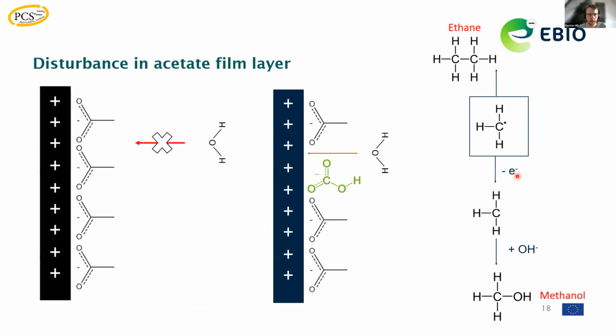So to summarize all this, what we think is happening is that we disturb our acetate film layer by the presence of the carbonate species in the electrolyte, thereby also allowing interaction of water with the anode layer, and thereby facilitating the formation of methanol in the end.